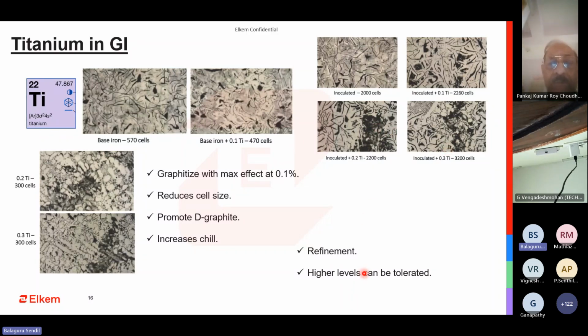Higher levels can be tolerated in gray iron as compared to ductile iron. It's more dangerous there. In gray iron, the amount of titanium can be tolerated. You can see the microstructure even at 0.3 titanium. I am able to tolerate it, but be aware that we used a very powerful inoculant to get this microstructure. A simple silicon calcium barium will not be able to get this microstructure.